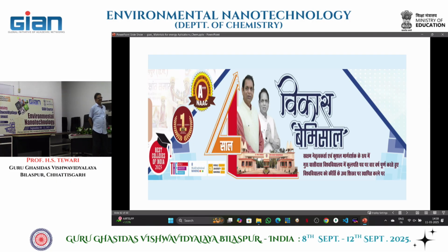Anyone have any question? If there is no question, then we can conclude. Green, because we are not using chemicals and other things. No chemicals. We are using some chemicals, but we are not using harmful chemicals. For that, we have used the extract of this flower. A number of properties will improve when you use this green synthesis. Particle size distribution is uniform. And XRD is also very good. If you use citric acid, then in the XRD there are a number of small impurity peaks also.